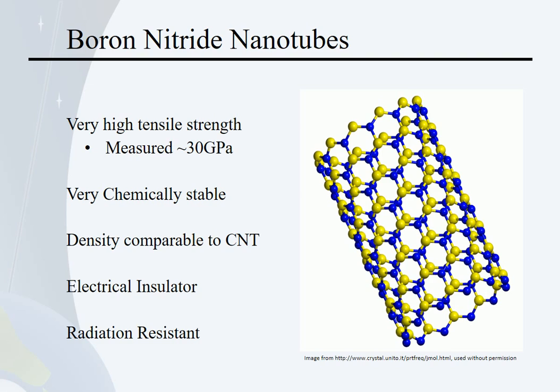Importantly, boron nitride nanotubes are also radiation resistant. So while nanotubes have been shown to be able to heal from damage, boron nitride will do a lot better about resisting that damage in the first place. So, trade-offs. But while different from carbon nanotubes, boron nitride deserves a place in our consideration. Its properties differ, but in most ways, it meets the goal. It falls within our criteria.